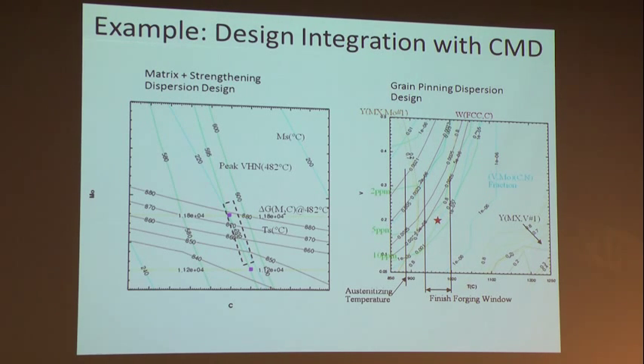Backing up to earlier stages of processing, this is an optimization of a composition variable and process temperatures where we're optimizing the grain refining dispersion that has to be present at the solution temperature to maintain the grain size we want. And there, we're constraining the solubility of that phase so that we can put it into solution at homogenization temperatures, precipitate it during hot forging, and have it have the right phase fraction and size during the austenitizing temperature to give us the grain refinement required.